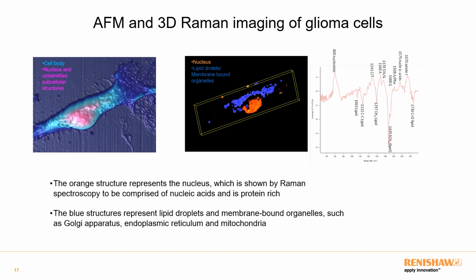Okay, if we then put the same cell on the Raman system and use our co-localization software, we're able to map the same area. Here we've done a volume image of the cell, and we've been able to isolate the nucleus simply by looking at the nucleic acid band around 800, and we've also been able to isolate other substructures. In this case we see lipid droplets and membrane-bound organelles. What I really want to show you here is that by using the two techniques in conjunction, we get more information about the sample.